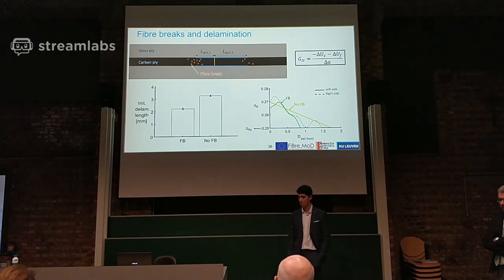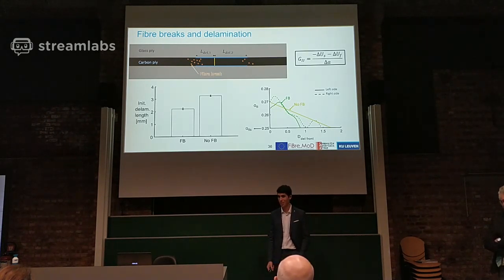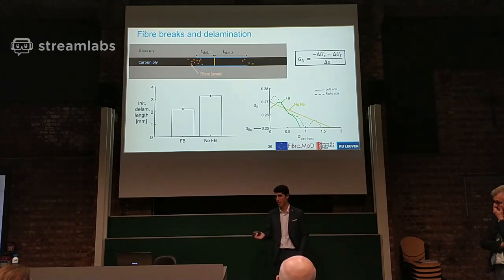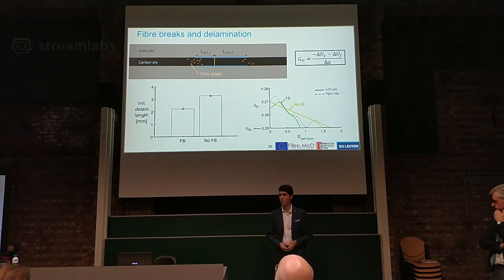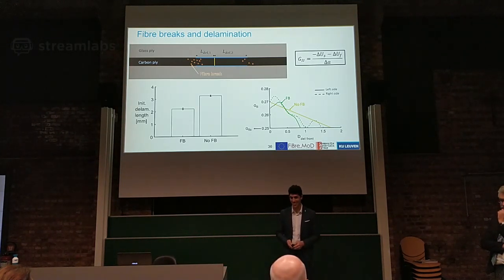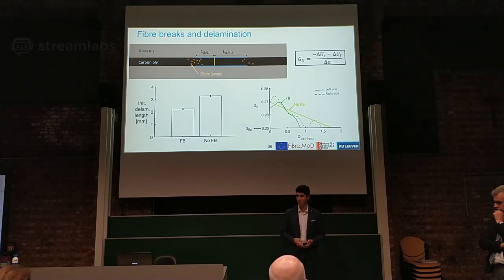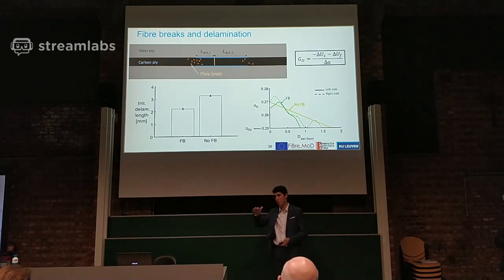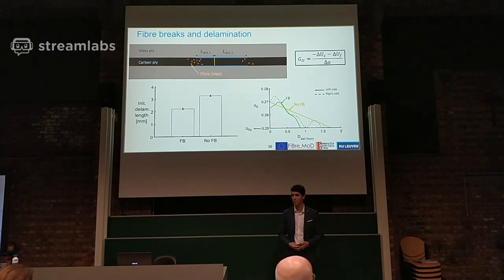Yeah. So using that to our advantage, we can probably have something even more gradual than the plateau we have. So maybe we extend the plateau if we have multiple fiber types, let's say 3. Let's not complicate too much. Let's say that the first plateau is happening because the carbon plies are fracturing. Then if we get a second type of fiber that will fracture afterwards, we can extend the plateau and then continue with the more ductile fiber types. So that could be a way. And if we have more and more fiber types, then maybe we can extend this plateau even more.